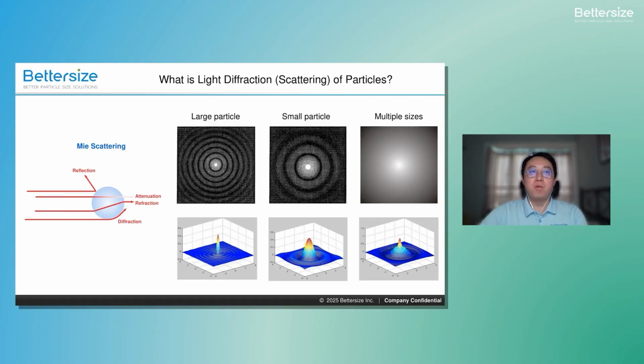If we fix the wavelength of the light and the distance between the particle and the screen, the Airy patterns will vary systematically with particle size, as shown in the picture of the large particle and small particle cases. One thing that needs to be mentioned is, in the real world, particles of mixed size will form a mixed pattern, as shown in the multiple sizes imaging.